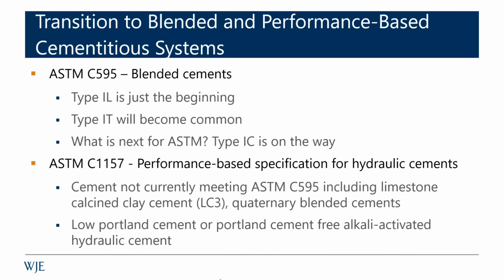Getting outside of the ASTM C595 blended cements is ASTM C1157. This is not showing up, I don't believe, in either of your specs. It's a performance-based way of looking at hydraulic cements, and it allows a lot more freedom for the person providing it. But you would know what's in it because they have to tell you. It would allow lots of other flexibility. And we've been working with a number of these products for data center construction, for example, where they're looking at significant reduction of 50, 60% off their benchmarks.